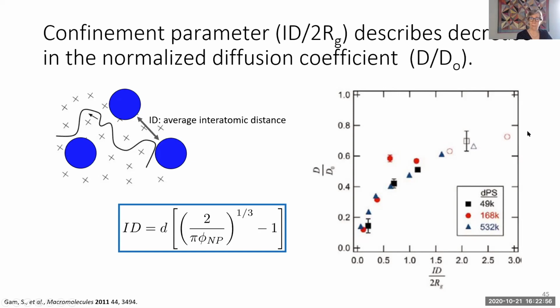And interestingly, at an interparticle distance that's quite a bit larger, ID over 2RG is 3, we're still 20 or 30% below the bulk diffusion coefficient. So even very far separation of particles still has a significant impact on the polymer diffusion coefficient. And so this was the first time that Russ and I used the ID over 2RG parameter.